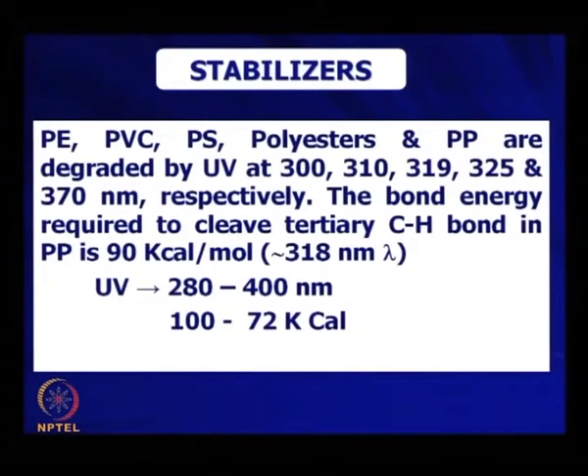So, polyethylene, PVC, polystyrene, polyesters and polypropylene are degraded by UV, ultraviolet light, in the 300 to 370 nanometer range. PE degrades at around 300, PVC at 310, PS at 319, polyesters 325 and polypropylene 370 nanometer. So, you see polypropylene degrades at 370 nanometer. So, polypropylene products are not suitable for outdoor exposure.